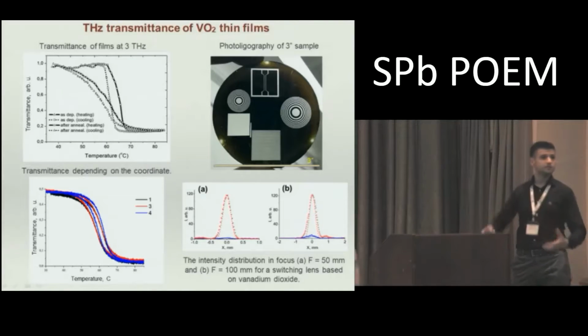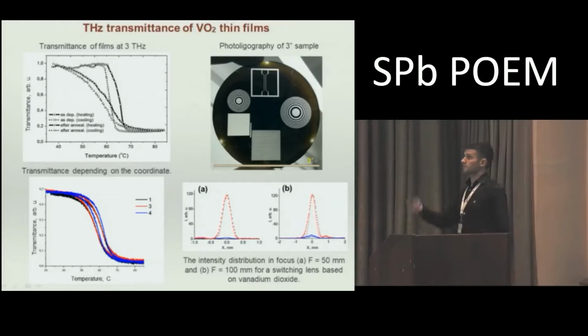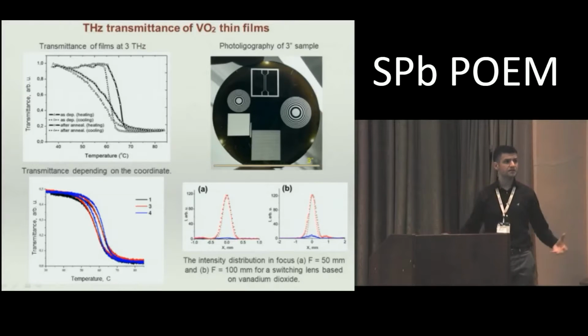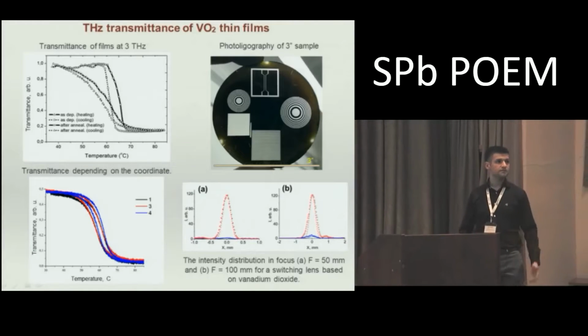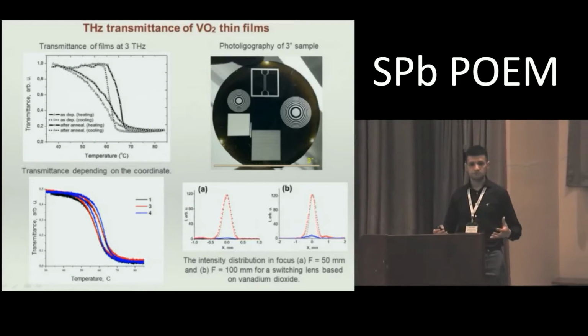So it is because of the morphology of our sample. We increase the grain size, we have a faster transition and fewer grain boundaries than we have in the sample without annealing.